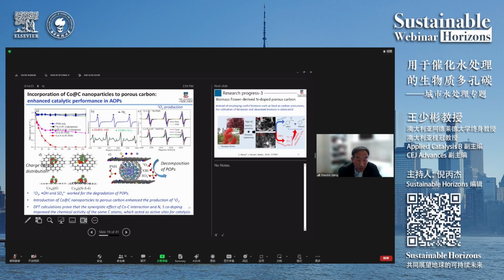So from those results, we can still see that in terms of the reactions, those metal-loaded carbon systems can give us very good activity, much better than the other system. And for such a system, the reaction mechanisms depend on both the radical and the non-radical systems. So in general, for the metal-loaded carbon systems, the singlet oxygen and also the radicals work for the degradation of those organics.